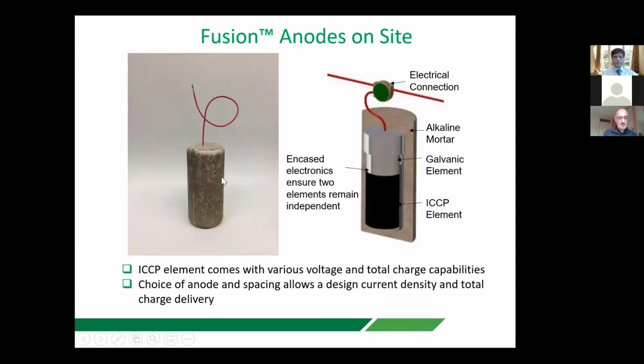And this is basically the product. It's just a small encasement in a cementitious material that again is saturated with lithium hydroxide, and that maintains the alkalinity for the galvanic element of the unit. But we have an ICCP element, essentially a voltage control, which is a battery.